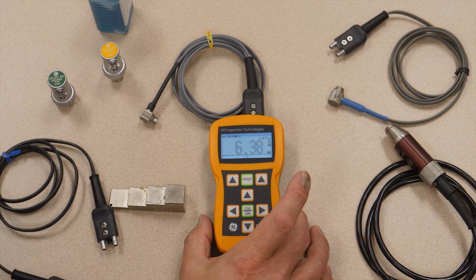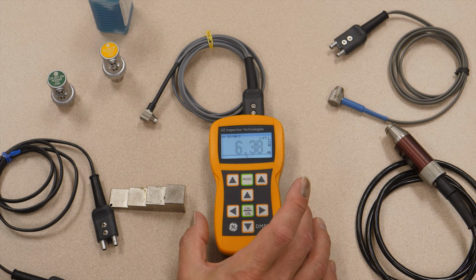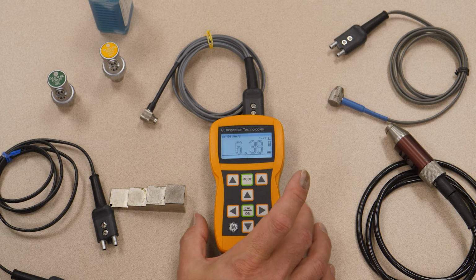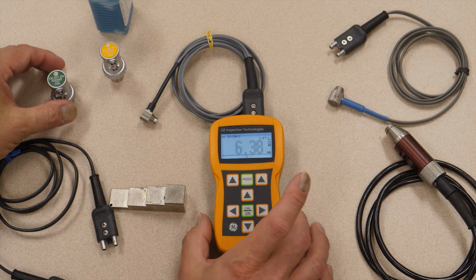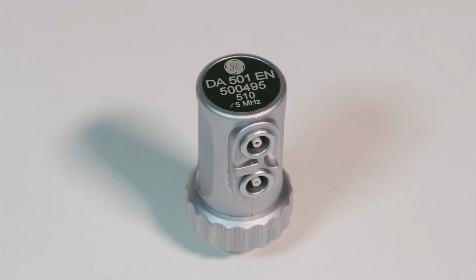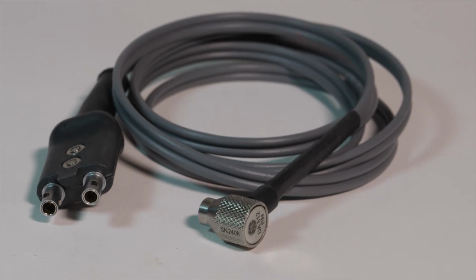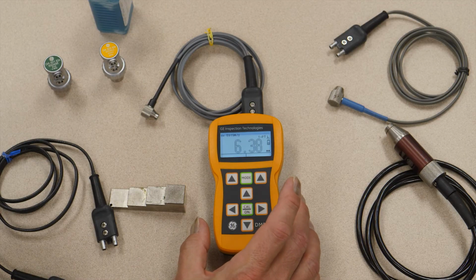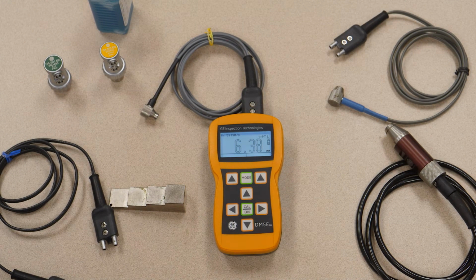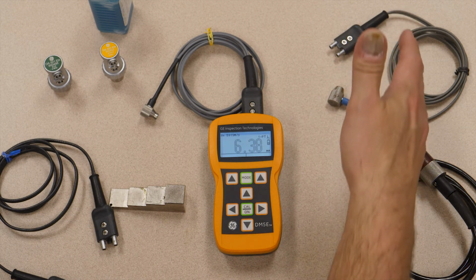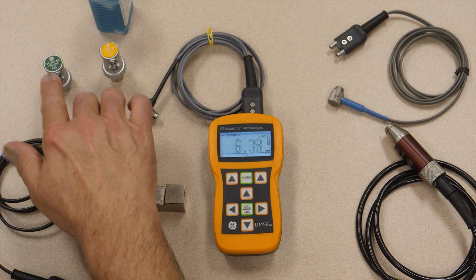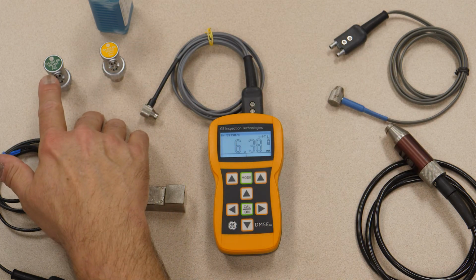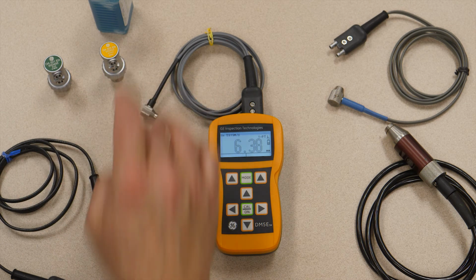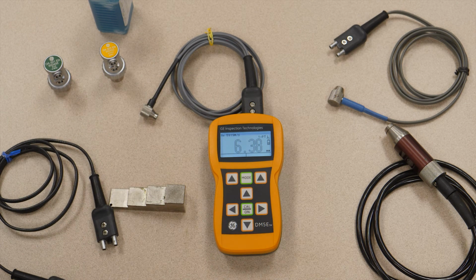It takes multiple backwall measurements through the steel only, ignores the coating thickness, and you get the raw base material thickness. Now, the dual multi-mode is only supported on this instrument with the DA501 probe and the DA512 probe. So a common question we have, folks will buy a DA503 or an FH2E, very commonly used probes, but only the regular dual mode is supported on these other probes. If you want dual multi to measure through thick coating, DA501, DA512 takes care of your dual multi needs.